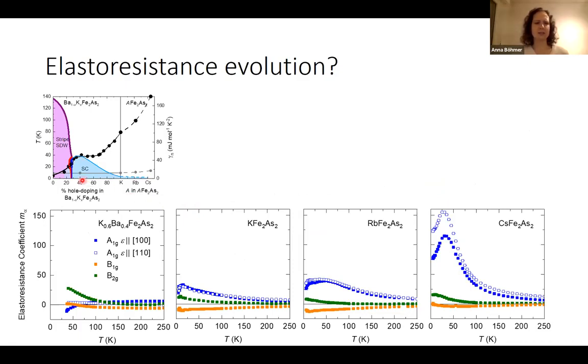We go again over this phase diagram from some optimally doped to the pure potassium, rubidium, cesium. In this one, which is still close to the stripe type order, we see an increase of the B2G elastic resistance, very similar to what we just had. We have small A1G and B1G components. We go further, the A1G component starts to grow, the B2G shrinks, and there's a finite B1G.